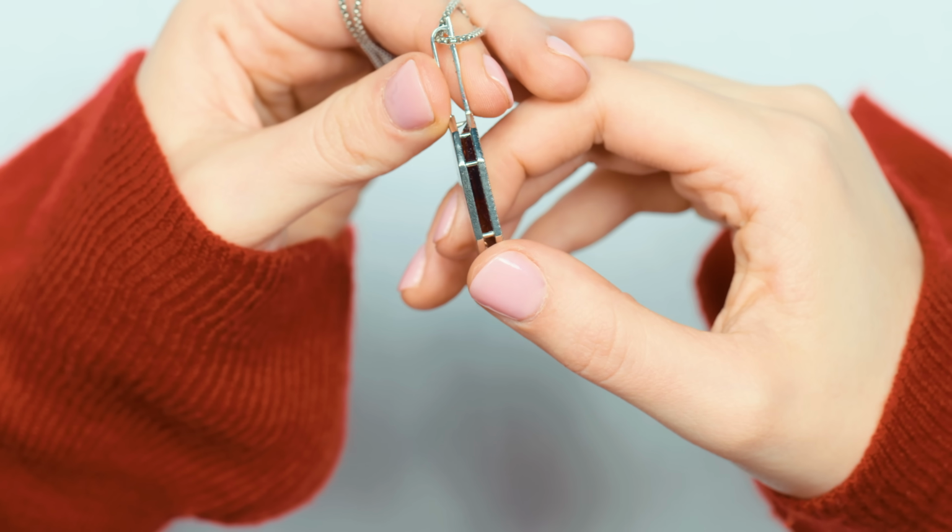And the beauty of doing these kind of cuts, I use the same critical angle. You don't change the physics of a gemstone. But I use that same critical angle in shallow stones to give it a little bit of brilliance. Things like a garnet that would typically be a little bit too dark in a really big stone, it wouldn't face up nice and bright. I can take things like this sunstone, which is also quite dark, and do a cutting to it, and you can look at the stone from the side, and you can see how relatively thin the piece is.